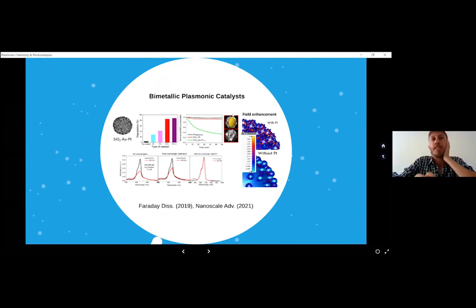In here, for example, we tested the idea of bimetallic plasmonic catalysis systems, and this is important. All the things we have mentioned so far concern how the reaction evolves when we excite the plasmon in the plasmonic material. However, plasmonic materials are not ideal catalysts for most of the important reactions, because they do not tend to have good properties for the adsorption and desorption of molecules, and for lowering the activation barriers of the reaction. That's what a good catalyst does, but plasmonic materials are not good catalysts for many reactions.